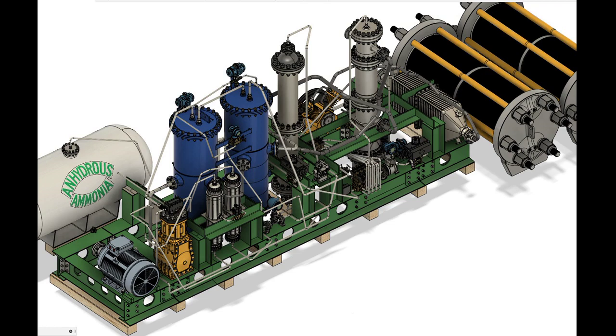It was found using data from the high-activity Wüstite catalyst that there was little need to increase the power density through process intensification of the reactor. The ancillary componentry should therefore be the main target of efforts to process intensify. Moreover, even if there was a need to process intensify, there is little ability to actually do this outside of improving the auxiliary systems, which themselves occupy the most space, as the reactor vessel, chilling, and reheating exchanger are relatively